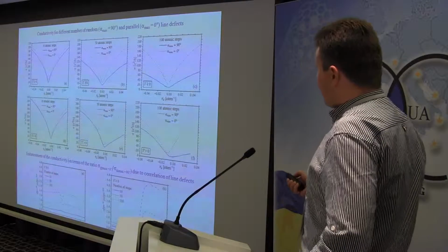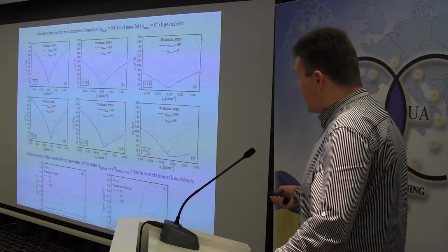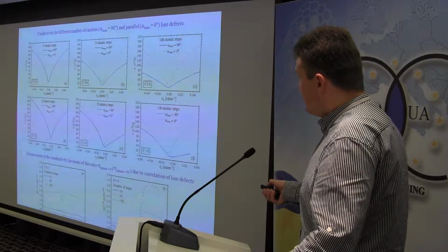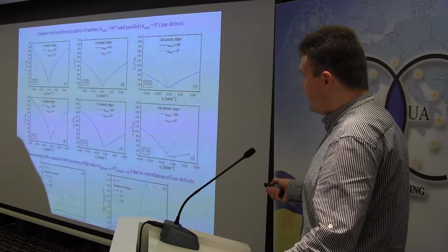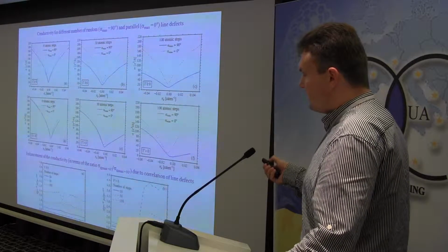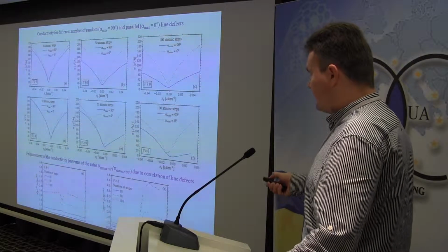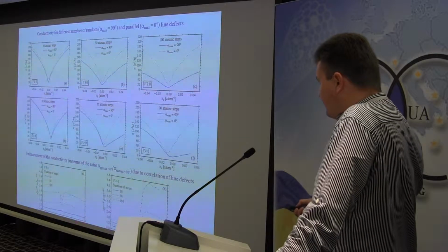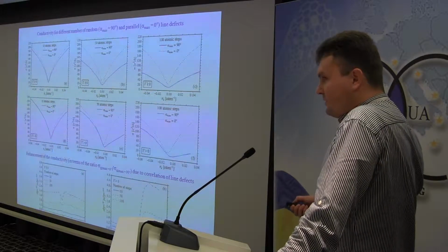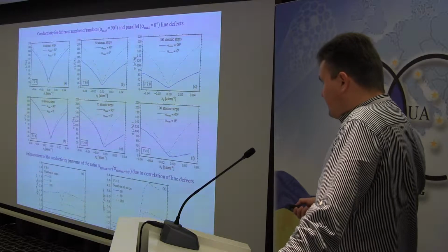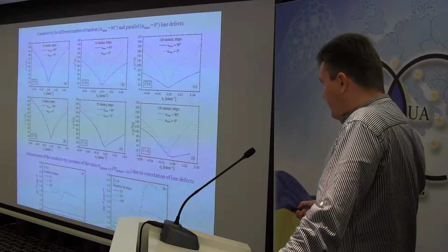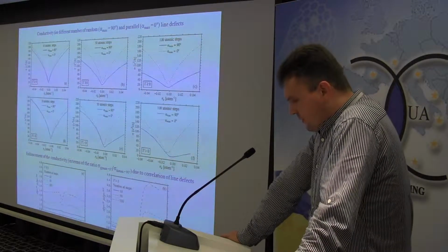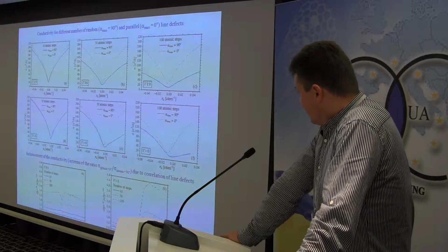Moreover, we proceeded for different numbers of lines. Here I write atomic steps. It means that we considered epitaxial graphene, where, due to the morphology of the substrate, there are some terraces and steps, and these steps act as line defects. And we calculated how conductivity increases with different numbers of lines in the lattice, with 10, 50, or maybe even 100 line defects.